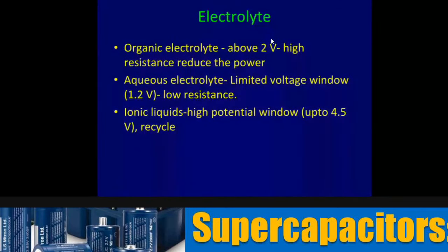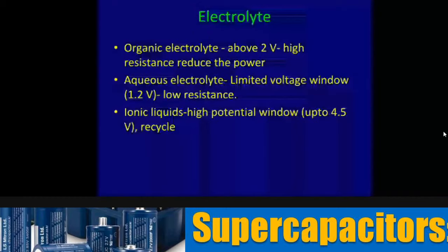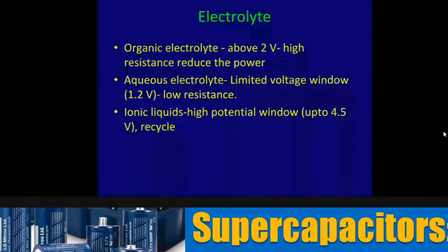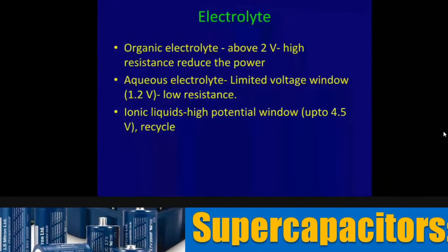So the next important thing when you try to design a supercapacitor is the electrolyte to be used. When you work with aqueous electrolyte, namely electrolyte like potassium hydroxide or sodium hydroxide, which is dissolved in water, because of the electro decomposition of the water, we will not be able to use this electrolyte beyond 1.2 volt. When you try to use beyond 1.2 volt, the electrolyte decomposes, thereby creating bubbles of oxygen and hydrogen, which will enormously hamper the operation of the device. And so aqueous electrolytes can be used only up to about 1.2 volt.